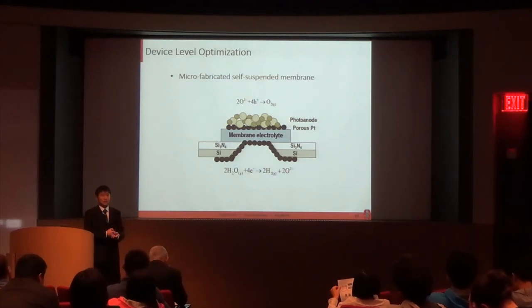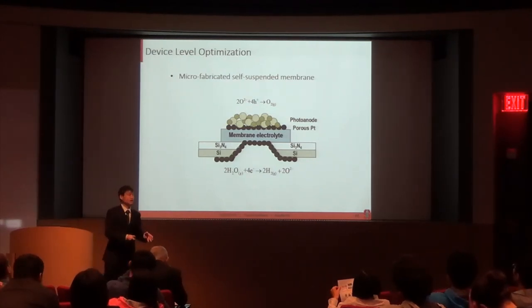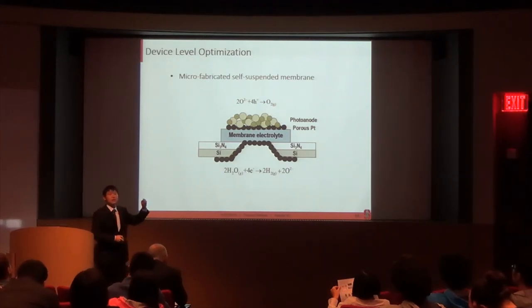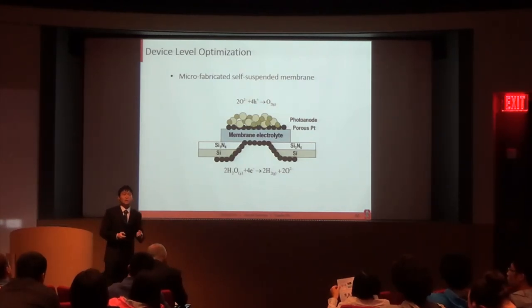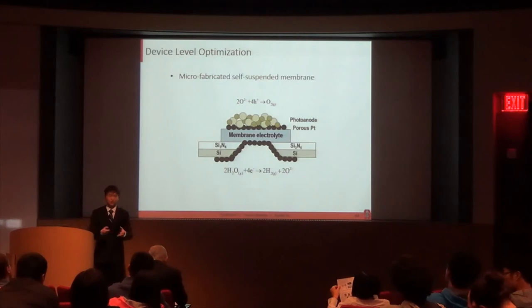On the device level optimization, we have been working on this self-suspended membrane with a very dense but very thin electrolyte to minimize the ohmic loss across the cell. And this is inspired by the micro-solid oxide fuel cells that are specifically designed for temperatures as low as 400 degrees Celsius.